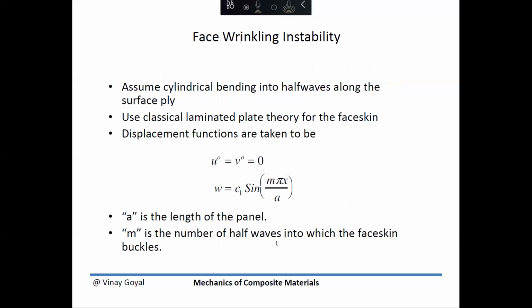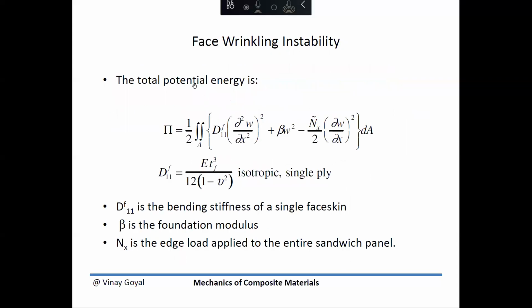For face wrinkling instability, there are closed form solutions. I want to discuss one such solution. The idea there is that the in-plane deflections will be close to zero, while the transverse deflection will be significant. Here, what we want to do is plug it into the total potential energy for a simplified problem. We're only looking at a beam type problem, so we're not looking at a plate, but the idea is to demonstrate and illustrate the energy method, the total potential energy.